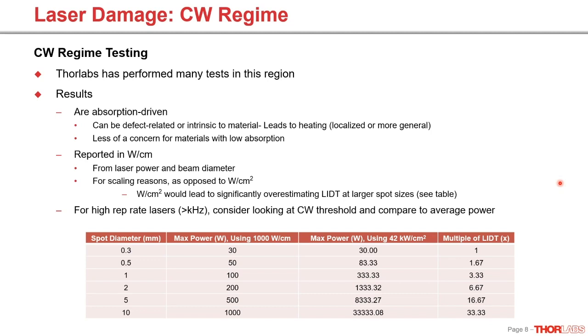And this is because the damage threshold scales with watts per centimeter rather than with watts per centimeter squared. And you can see an example of this in the below table. So if you have a 30 watt laser at the smallest spot diameter I have there, which is 0.3 millimeters, and you scale with the watts per centimeter, you will safely scale with the damage threshold. But you can see that if you use the beam area in this column, you will rapidly have much more power than the part failed at. And obviously that's something you want to avoid.